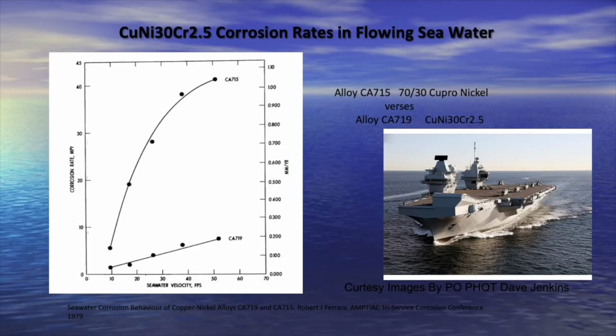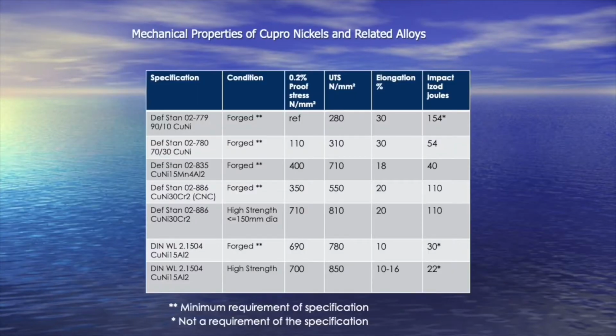Here we have a typical corrosion rate of flow rate, so impingement rate of copper nickel chromium versus 70-30 cupronickel. One of the advantages we can see is that the flow rate that you can put through tubes on the copper nickel chromium is much higher, and therefore systems can be more efficient. The strength of copper nickel chromium is quite interesting. Should enable people and engineers to design lighter, lower cost components because of the mechanical strength of the material. It rivals that of a 316 stainless steel.